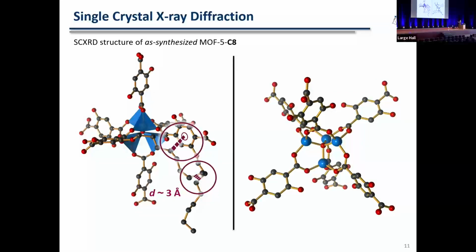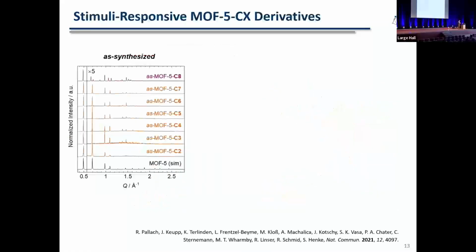And so you get basically this oxygen atom here in the center of the node moving up a bit, and the zinc atoms here are coming out a bit. Therefore, this bond is a little bit longer, and this one is a little bit shorter compared to the conventional MOF-5. So it's a slight distortion of the node, which then results in the rhombohedral distortion of the entire structure. So you have slight changes in the angles.